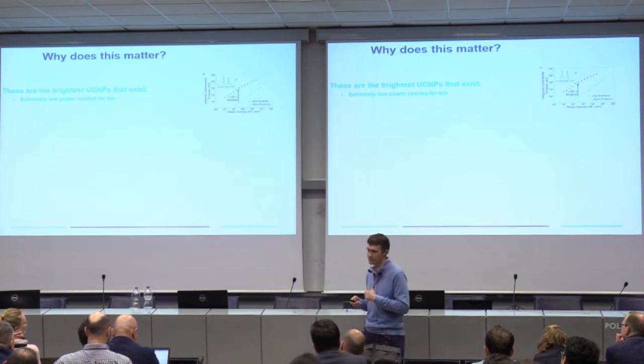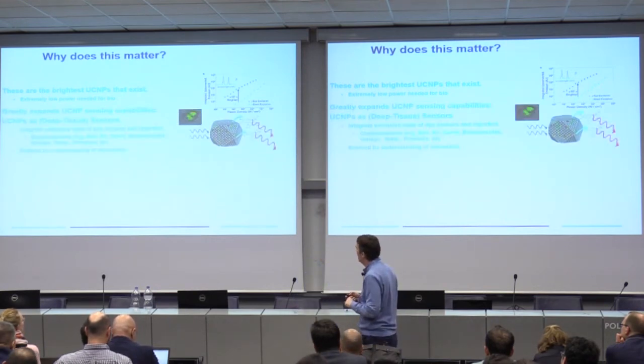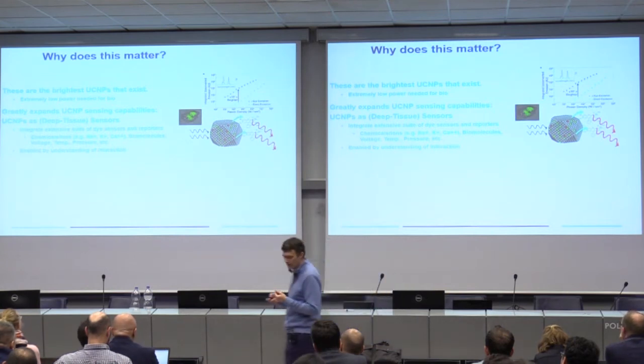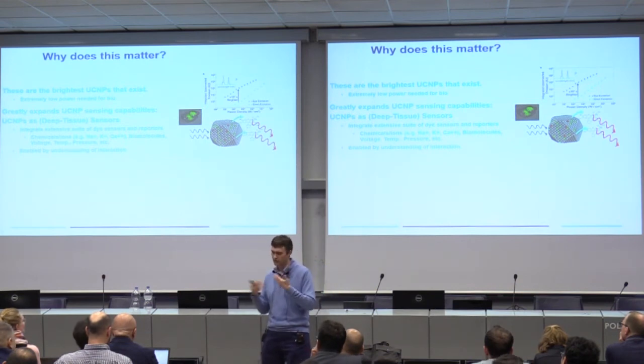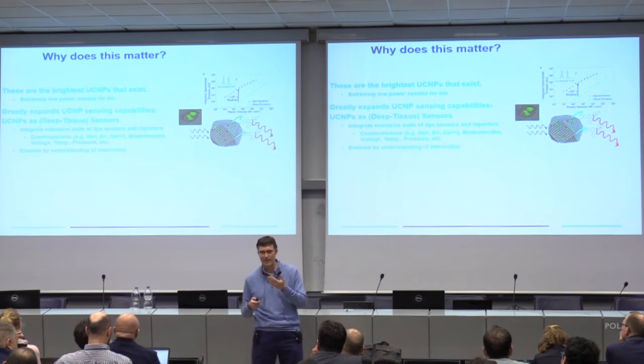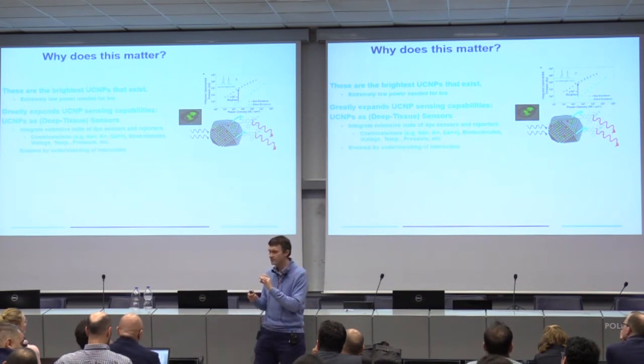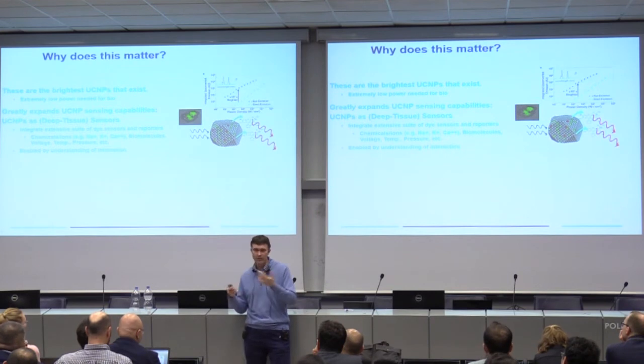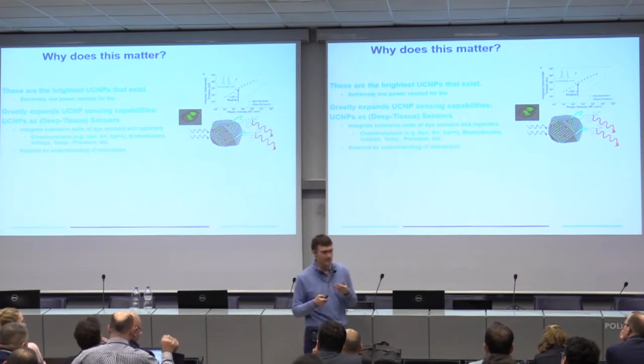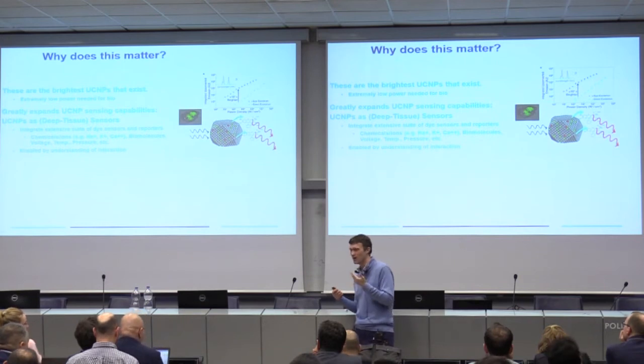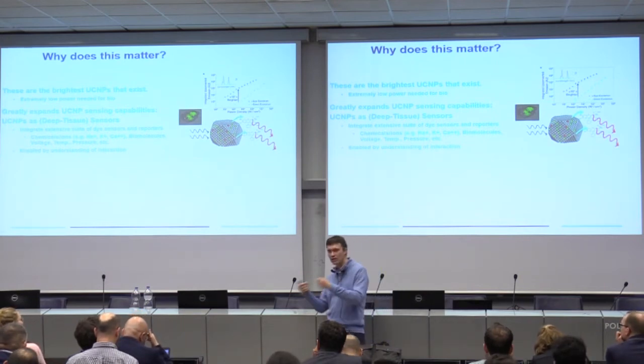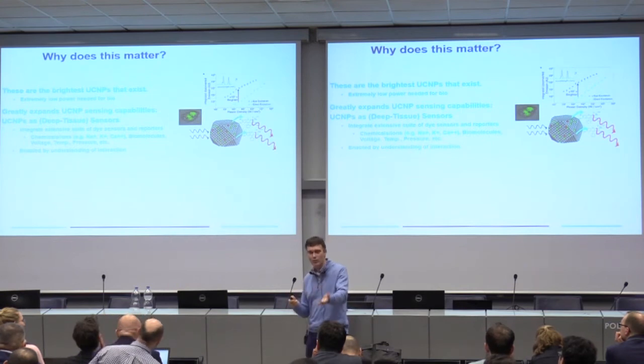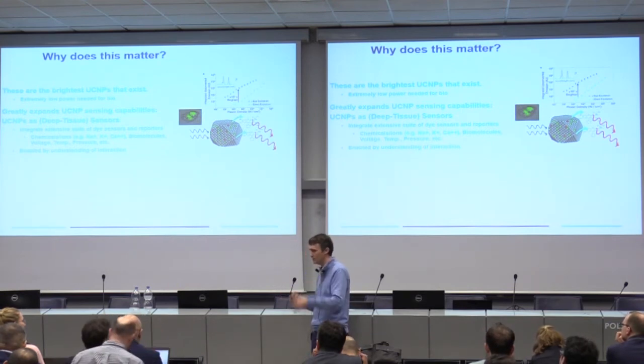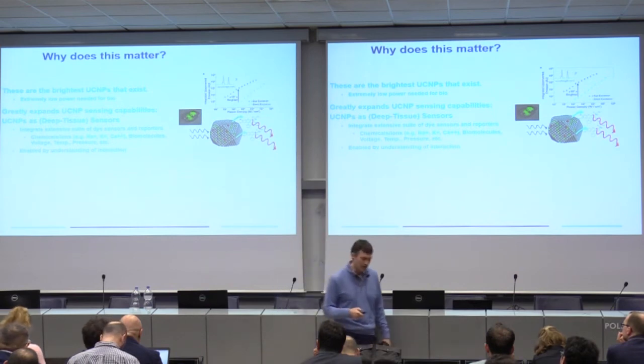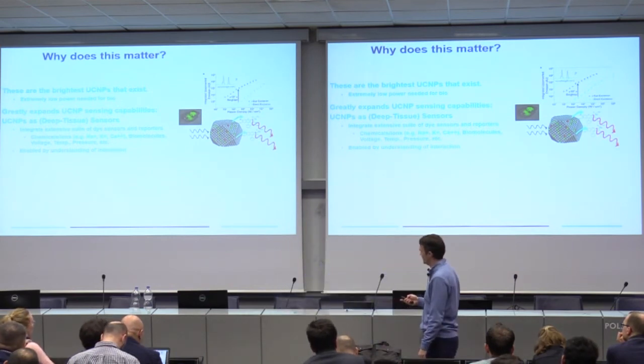In fact, we showed that when you encapsulate them, these things last for a while. The other reason this matters, to understanding how energy goes back and forth between, say, fluorescent molecules or between molecules and upconverters, is that upconverters themselves aren't great sensors. But dye molecules, people have engineered all sorts of organic molecules to sense everything from ion concentration to pressure to temperature, et cetera. And so now you can interface those two capabilities and have them work deep in tissue because you're using infrared light to ultimately interface with the molecules. So that's probably another big reason this matters.